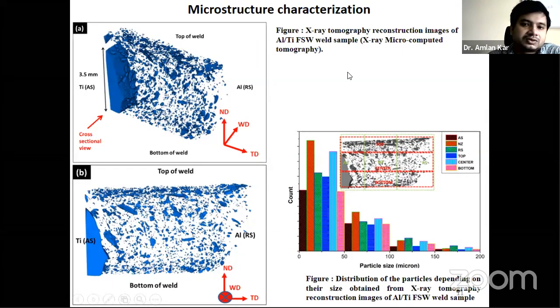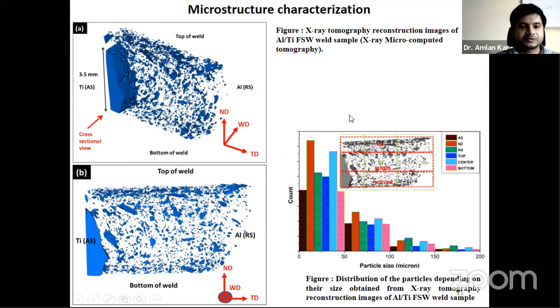Then we have done the tomography of the weld zones, and in this tomography image we are omitting the aluminum. We are only seeing the deformation or the distribution of the titanium particles. So you can see that from the microstructural or macro view, the particles are inhomogeneously distributed. Here also you can see there is no sort of arrangement.